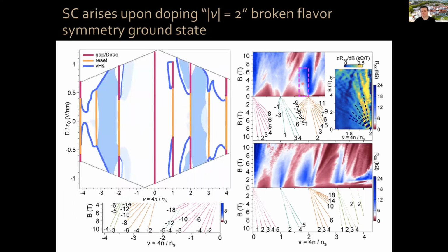the superconductivity, okay? What happens is that usually at low displacement field, you're filling your system with electrons, and then you're resetting close to charge neutrality, and now you continue filling your system with electrons. However, it seems that at large displacement field, that phase transition that at low displacement field leads to a reset near charge neutrality, but for electron doping, at large displacement field, the presence of the Van Hove singularity triggers a reset earlier, at an earlier filling, okay?